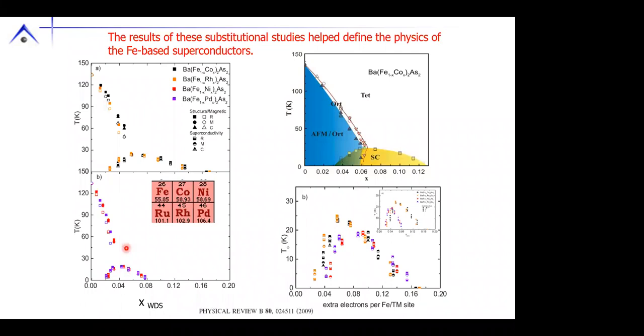We could see that this Tc dome scales with the number of extra electrons we put in. We can see that as we suppress this antiferromagnetic orthorhombic transition, we see them split and separate. We see a dome of superconductivity, and we see a backbending of this transition. This phase diagram, which has become the iconic one for the iron-based superconductors, helped inform the theoretical understanding and motivated our ability to understand these compounds.